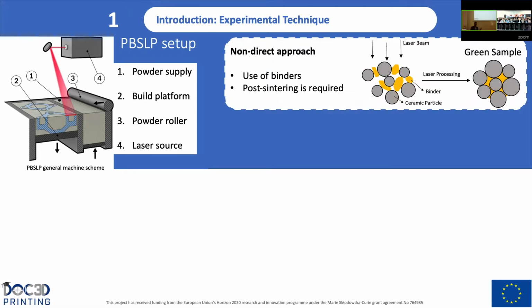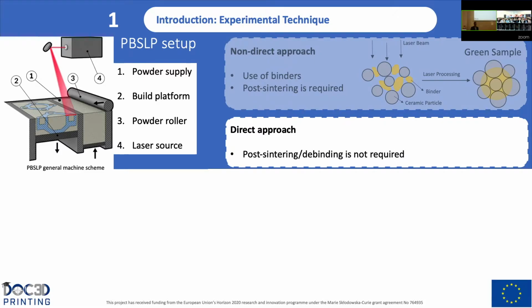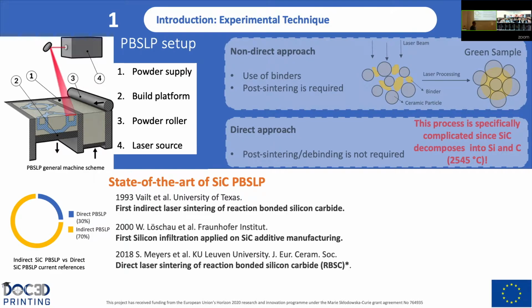In general, this technique is divided into two approaches, or two methods. Non-direct approaches, which require the use of binders and post-sintering. And on the other hand, direct approaches, where post-sintering and binders are not required. But this process is especially complicated since silicon carbide decomposes into silicon and carbon, as we saw, in excess of 2,545 degrees. Now, regarding the state of the art of this material, silicon carbide, and this technique, at present,